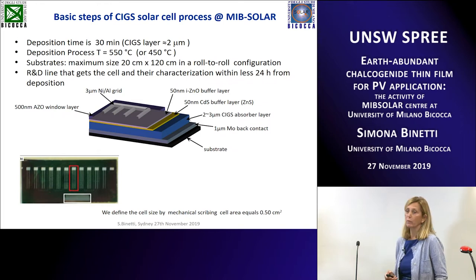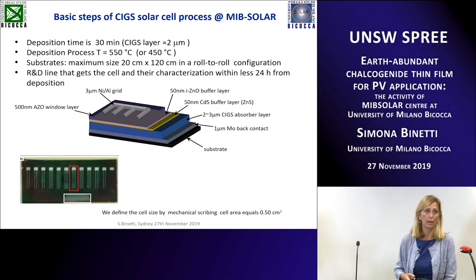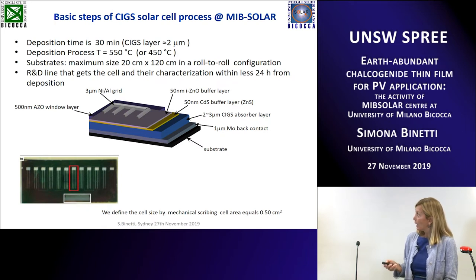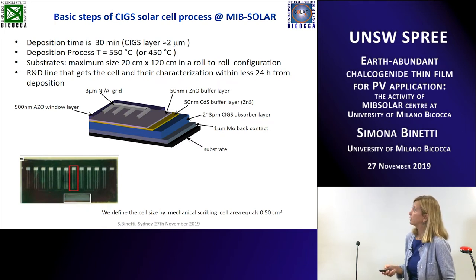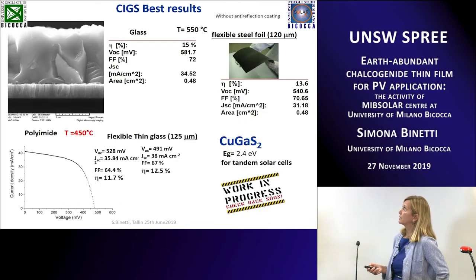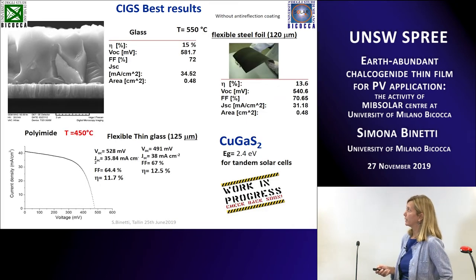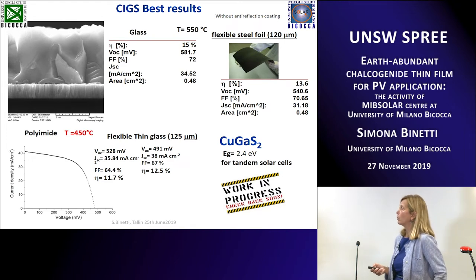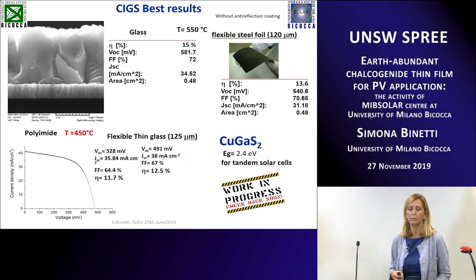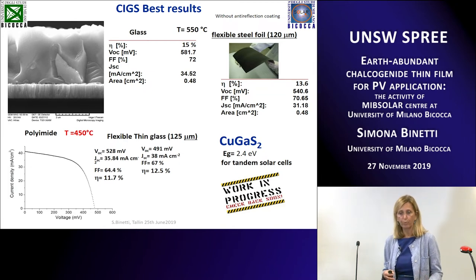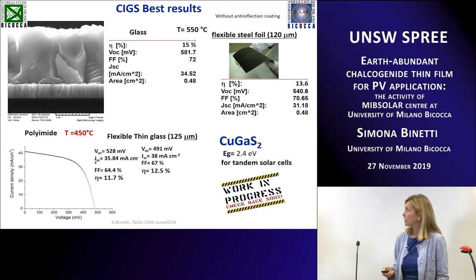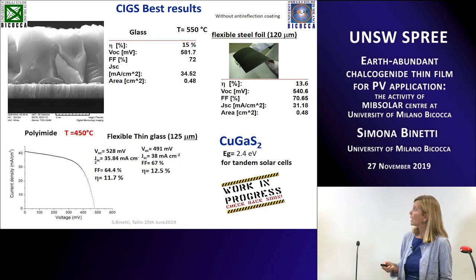And then we can make the solar devices with the standard configuration, in which we use cadmium sulfide by bath deposition on the absorber layer. This is our best result that we got on different types of substrate: glass, flexible steel, polyimide, and flexible thin glass. Now we are optimizing this system. We are changing part of our system in order to deposit by this technique CGS, which has a very high band gap, to make tandem solar cells. But this is just new work, and I cannot show you anything.